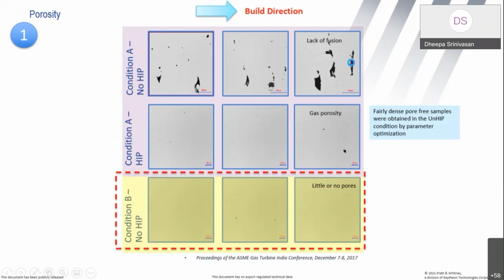When we started, it was quite scary because we did get a lack of fusion at every single layer, a lot of porosity that has crept in, either due to the entrapped gas or due to moisture or whatever. But soon enough, we optimized the process parameters and we tried two conditions, one with hot isostatic pressing. And normally this hot isostatic pressing is done for all the hot section parts, irrespective of what part it is in an aero engine, so that you delay the fatigue failure due to inherent defects. And typically hot isostatic pressing is done to close the pores in the grain boundaries in order to enhance the creep resistance of the material.